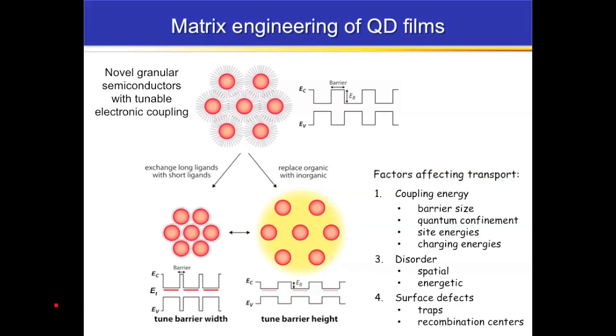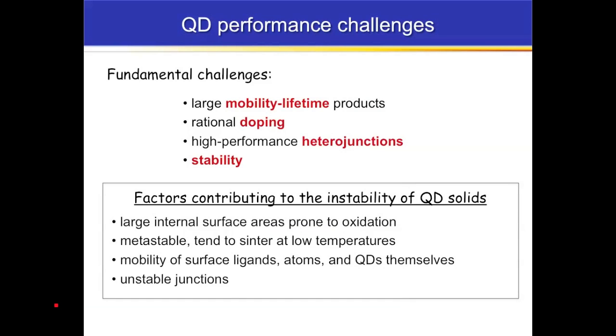And so we adopt a strategy that mixes these two approaches, and this allows us to tune coupling but also pay attention to the other factors that are important in charge transport in these films. One of those factors is disorder, including spatial disorder and energetic disorder in the film. And then the other factor that's very important is surface defects, including traps and recombination centers that can lead to loss of current. Okay, so I'll come back to that in a second.